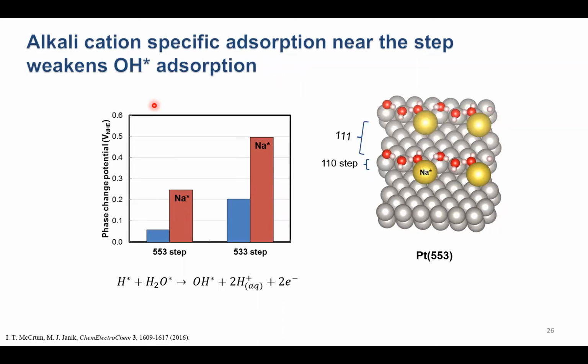We still need to explain why they shift with pH. And so again, we wanted to study whether or not the alkaline metal cation could sit close enough to the surface at high pH that it would interact with various adsorbates on the surface. And we find that that's exactly what happens. We find it's favorable for an alkaline metal cation to sit close, especially to the step edge of a step platinum surface. We call this specific adsorption. We say that it's favorable. Again, we'd see only minor amounts of electron transfer, so we would never see an adsorption peak for this in a CV. Really, what we're saying here is it sits close enough to the surface to give up some of its solvation. It sits too close to the surface for water to be in between the cation and the surface.